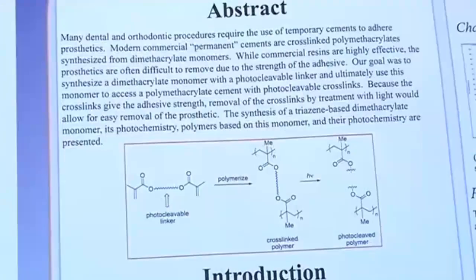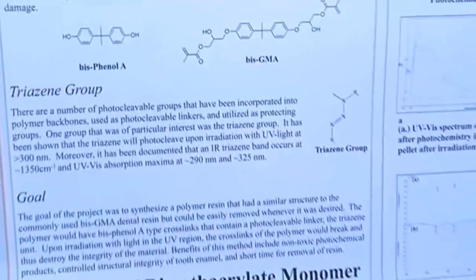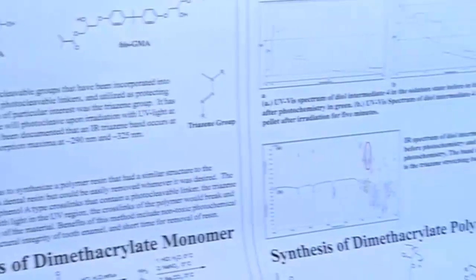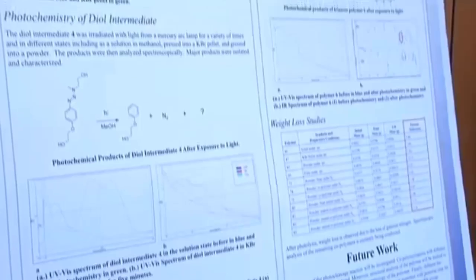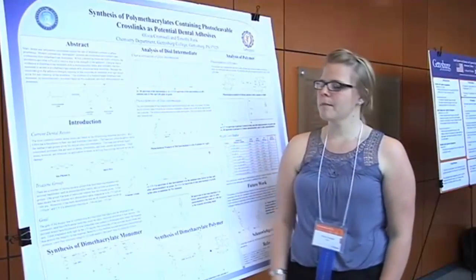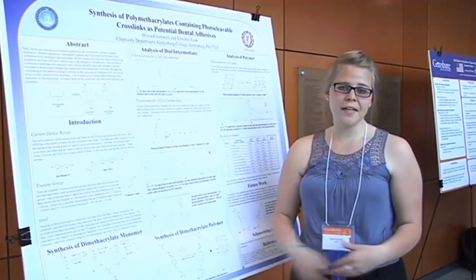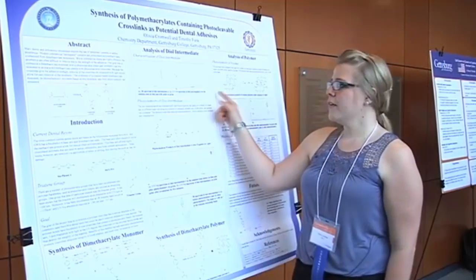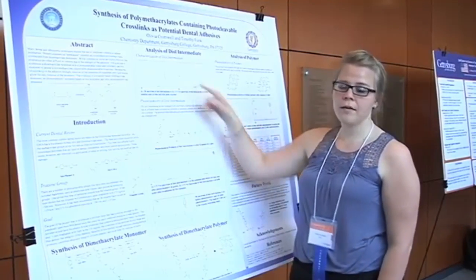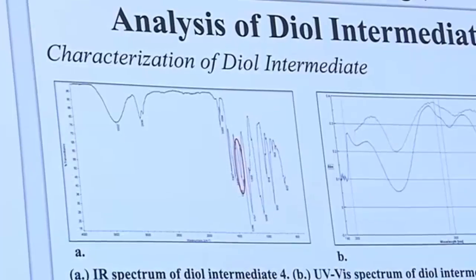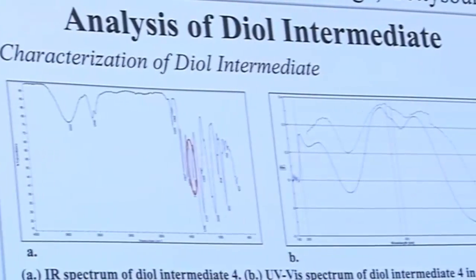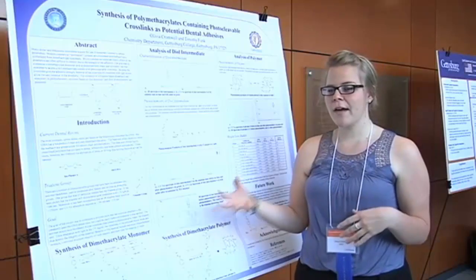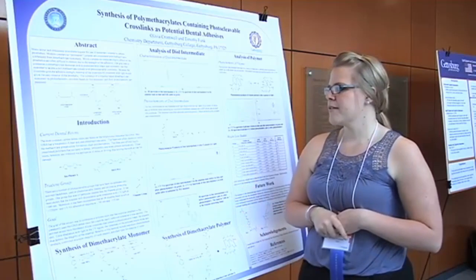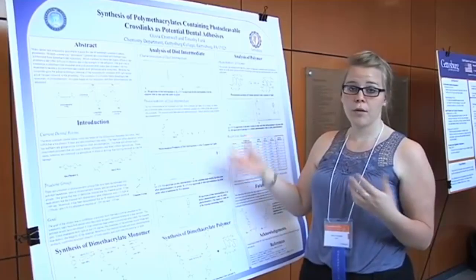What we looked at first was how it performed in solution and in the solid state. We used IR spectroscopy and UV-vis spectroscopy to study the presence of the triazine unit. Here's the IR spectrum, and we can see that it has a diagnostic peak at around 1350. The UV-vis spectrum has two peaks here, one around 290 and the other at 325. We studied this in the solution and solid state because we anticipated our final polymer to be insoluble. And so what we saw was that there were diagnostic peaks.